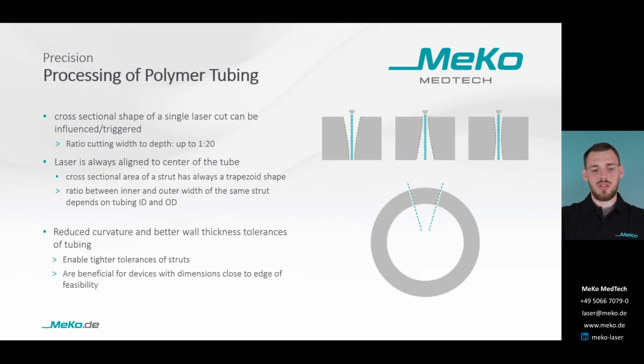When we now look at the shape of the cutting slit, this can be triggered during setting up the laser machine. Important parameters here are the focal length and location of the laser focus along the material thickness. The upper figure shows the three extremes triggered by the focus position. In most applications, the goal is a cutting width that is as consistent as possible over the entire material thickness, as shown on the right.